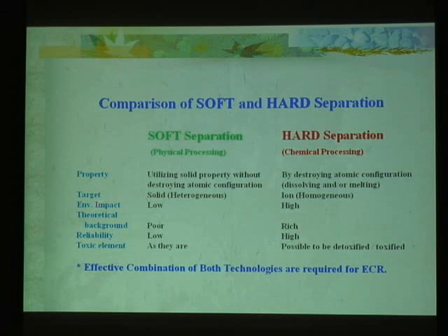Then environmental impact is lower in soft separation, but high in hard separation. But what about theoretical background? Soft separation has very poor theoretical background, because no two solid materials are completely the same. This is a heterogeneous separation process, so the theoretical background is very low compared with hard separation. Then the reliability is very low in soft separation, but high in hard separation.